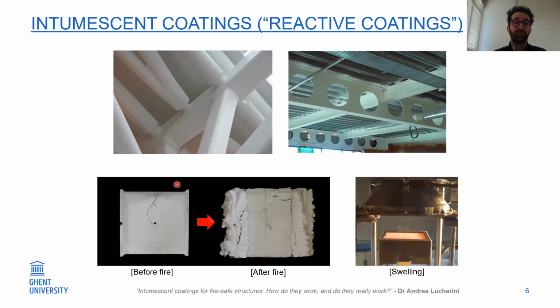So you can see an example before the fire. This is an I-beam coated with Intumescent coating. And after the fire, you can see how this beam section would look like. The char is characterized by low thermal conductivity and low density, which insulates the structure from the fire and keeps the temperature of the steel substrate down.